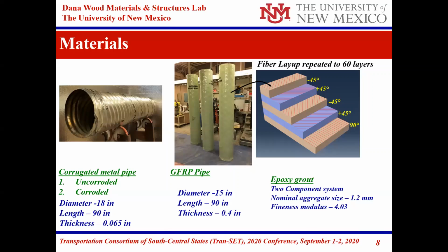And we came up with a grout that's basically an epoxy grout, which is a mix of a two-component epoxy system with aggregate, with a mix of aggregate of different sizes at a fineness modulus of 4, that needed to be a flowable grout so that we can pump it in the annular space between the corrugated pipe and the GFRP.